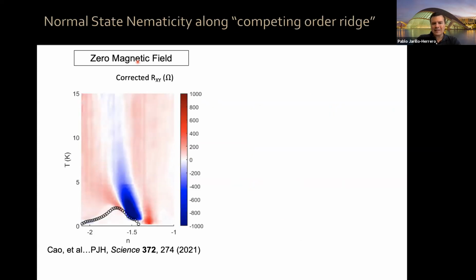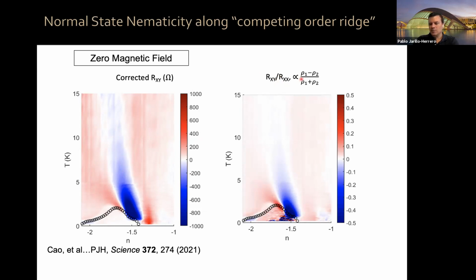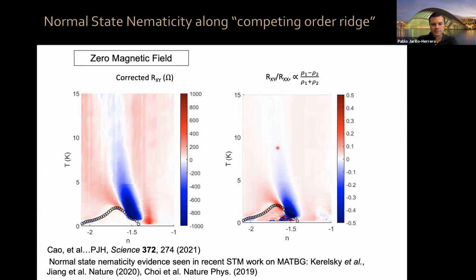Now, at zero magnetic field, we measure RXY and we correct, because there can be various artifacts that can give you a finite value of RXY. We correct for all of those, and we have this very strong signal here in this region, okay? In fact, we can normalize RXY by RXX, which is proportional to rho 1 minus rho 2 divided by rho 1 plus rho 2. And we can see that there is a very strong, of order 50%, anisotropy in the system in that region where we also see the resistivity ridge, which leads to a competing phase, okay? Superconducting phase. So I should mention, by the way, that normal state nematicity has also been seen in recent STM work by various groups.